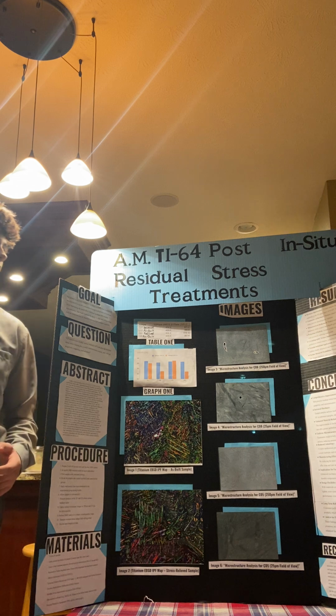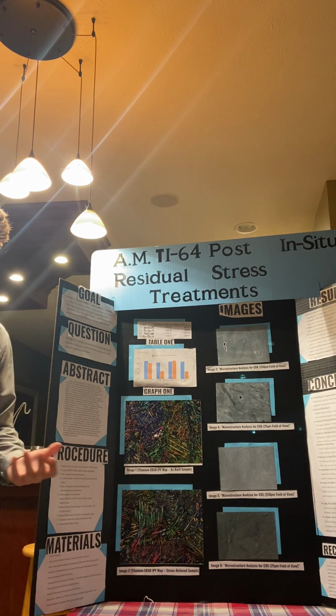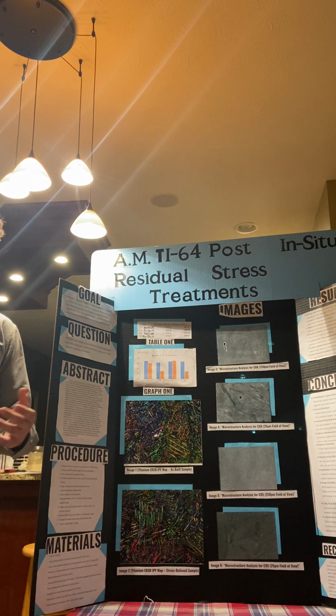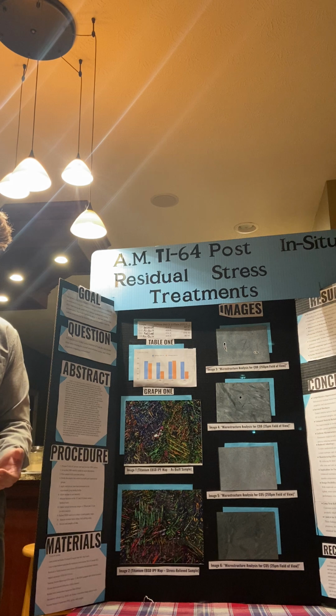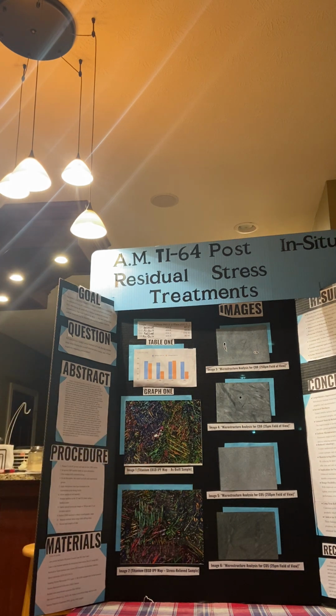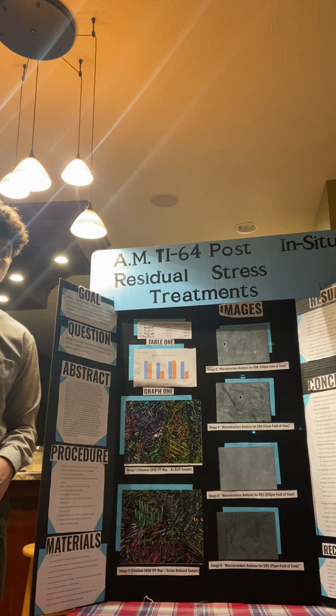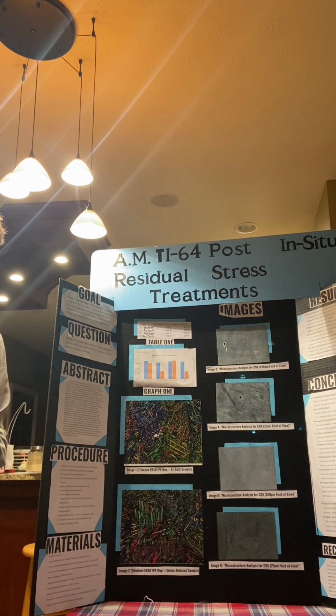So just with the results, this treated sample showed significantly higher hardness, especially in the XY plane, up to 410 versus the 370 in the controls. The consistency of hardness: the hardness values in treated samples were more uniform, while control groups showed greater variation. Like I said, reduced defects, there are no defects in the experimental groups, which is again great. There's texture improvements. So yeah, there's so many further research possibilities with this. In conclusion, there's increased hardness, enhanced material reliability, uniform microstructure, reduced anisotropy, manufacturing efficiency, and implications for future products.